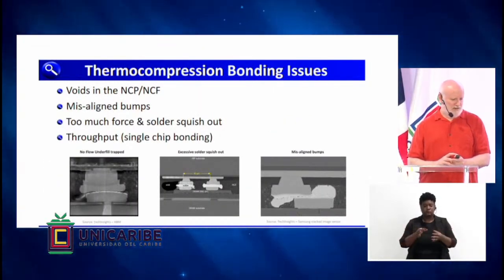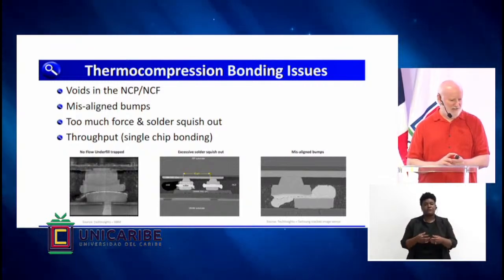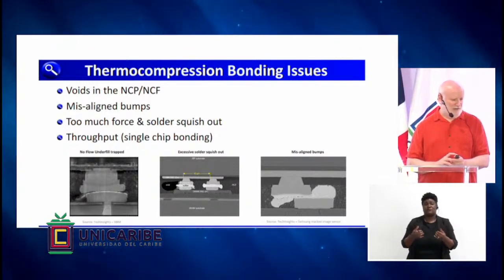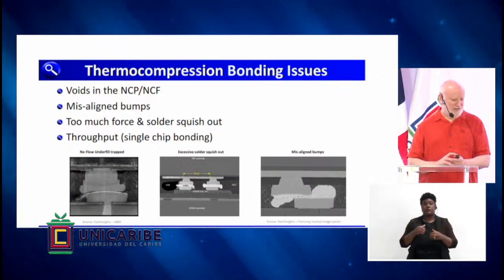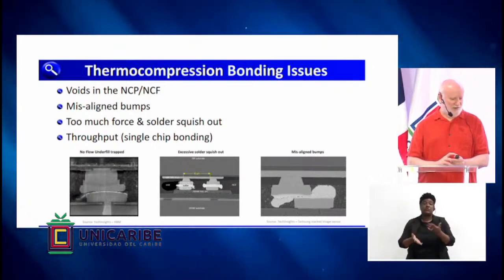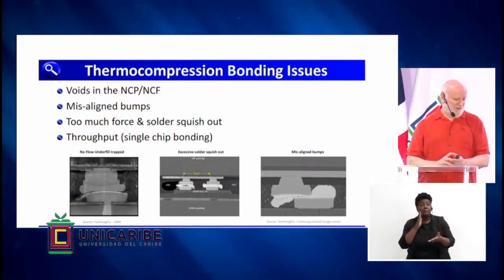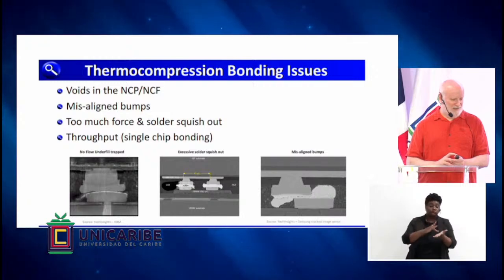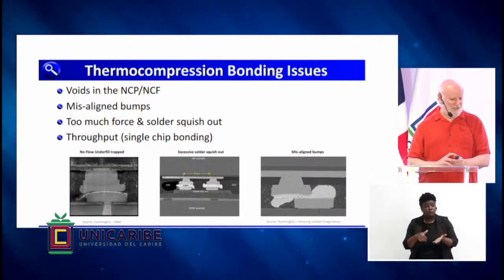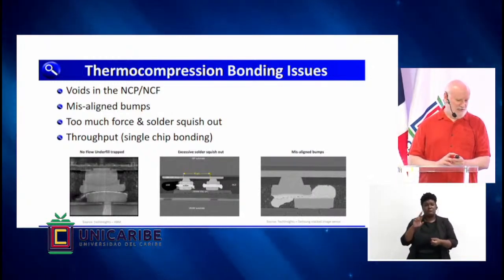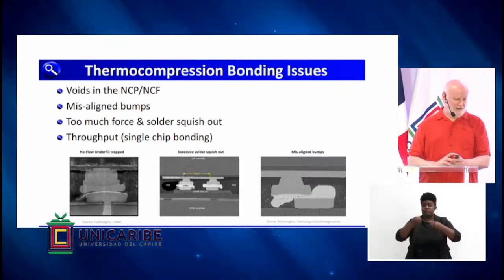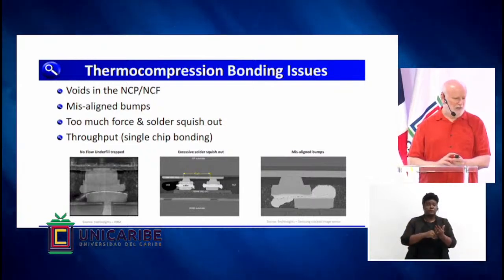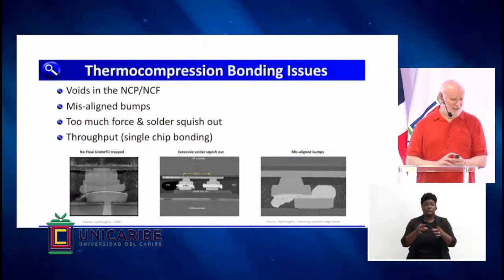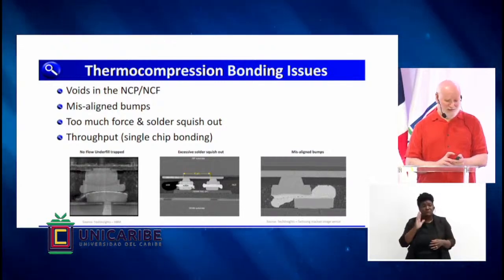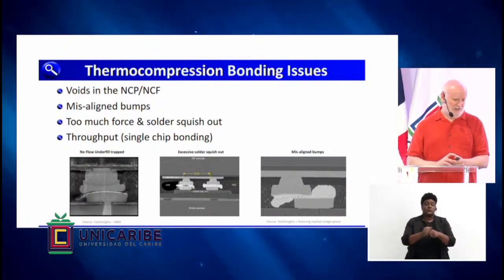So you can see, again, there's all kinds of issues that can arise. The one on the left is a non-wet. The joint hasn't been made. In the middle, you over-bonded, and you get the solder squishing out at the sides. And then the one on the right is misaligned. If you're working on the line, these would be all things that you'd work to correct and make sure they never happen.